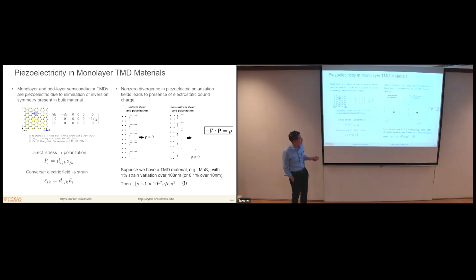Okay, and if you take the dielectric or the piezoelectric moduli of these materials, and you just calculate in a back of the envelope way, what kind of charge density would you get through this mechanism if you had, say, 1% strain variation over 100 nanometers, right, which is very consistent with what we had measured, then in bulk form, you would get something of the order of 10 to the 17 electronic charges per cubic centimeter. In a monolayer, that corresponds to something of the order of 10 to the 10th electronic charges per square centimeter, which is actually quite a lot, right?